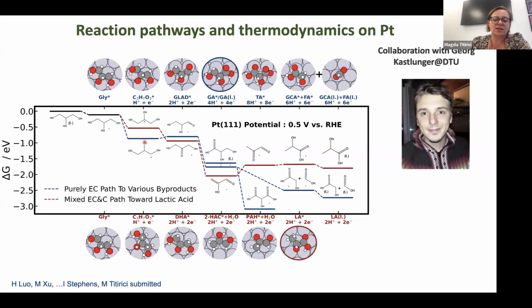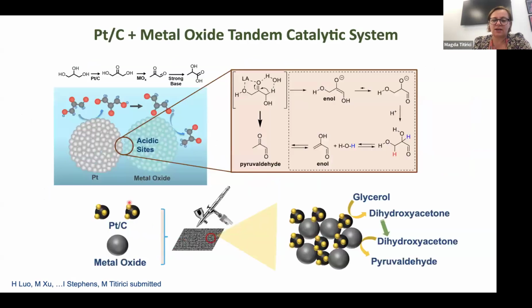And so we want this pathway, which is a mixture of electrochemical and chemical pathway. In order to have this achieved in a real catalyst, the idea was to still use platinum, and the platinum nanoparticles would do electrocatalysis of glycerol to dihydroxyacetone. We want to stop the electrochemistry here and then have the rest happen chemically. So the catalyst that would take this dihydroxyacetone and convert it to pyruvaldehyde would be something from the literature that would have a lot of Lewis acid groups.